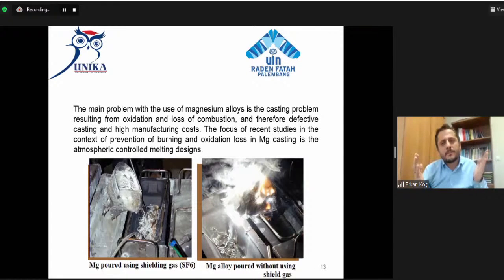But the main problem: is it easy to get magnesium? Not easy. The main problem with the use of magnesium alloys is the casting problem resulting from oxidation. If you use it without shielding gas, magnesium oxidizes easily, with loss of combustion, and therefore ineffective casting and high manufacturing cost. If you use shielding gas, SF6, sulfur hexafluoride, you can see here a clean metal. The focus of recent studies in the context of prevention of burning and oxidation loss in magnesium casting is atmospheric controlled melting designs.